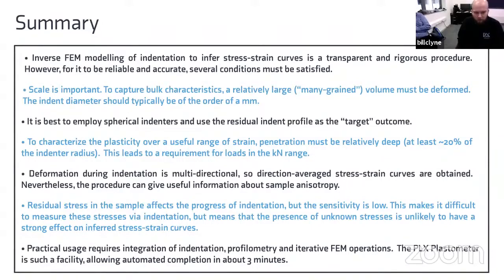Spherical indenters are typically the best ones because they don't have any issues such as sharp corners, so there's no problems with the modeling. And the residual indent profile is a much more sensitive outcome to the properties than the typically used load displacement plot. To characterize plasticity over a useful range, we've got to probe relatively deeply, around 20% of the radius, which means if you're going to use a millimeter-sized sphere, you need loads in the kilonewton range.